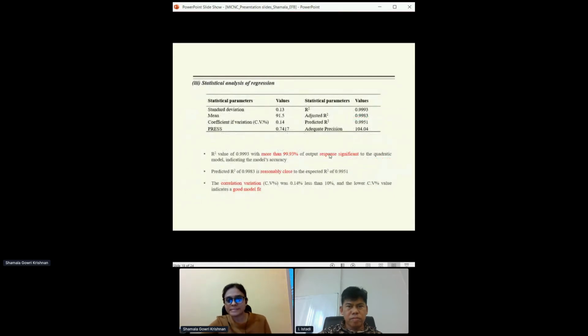Moreover, the statistical analysis of regression coefficient shows the R square value is more than 99.93%, which indicates the model output response is significant and the model is fit. Besides, the coefficient of variation, the CV percentage, was 0.14%, which indicates it is a good fit model and it's reliable.